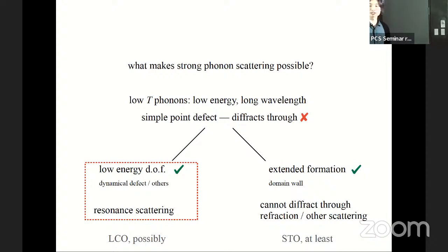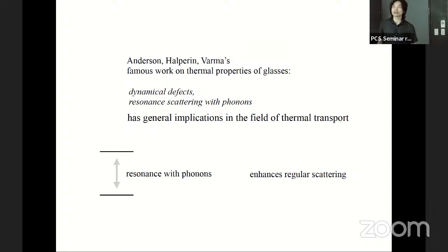So now let's explore the idea of resonance skew scattering. The idea of resonance scattering, not skew scattering, just usual resonance scattering, became important because of Anderson, Halperin, and Varma's famous work on the thermal properties of glasses. Glasses are very complicated materials. They have a lot of defects at all energy scales, including some dynamical defects at low energies. For example, there are two-level system defects. If the two levels match the energy of certain phonons, then there will be resonance. And the resonance scattering of phonons with these dynamical defects in the glasses will produce interesting thermal transport behavior. This has had a very important impact in the field of thermal transport.